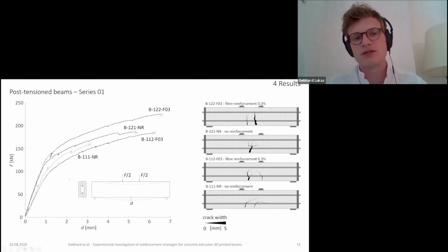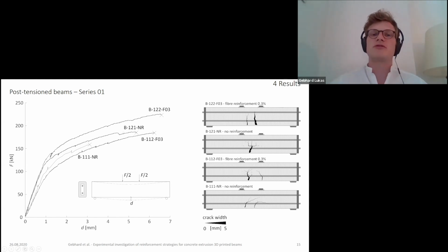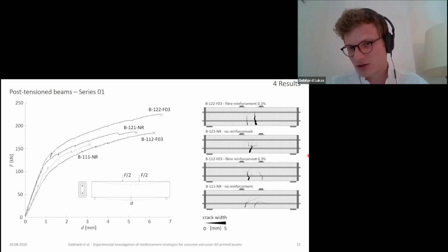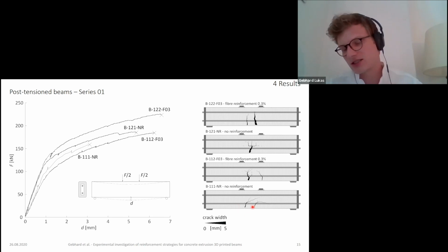So again, only series 1, where you can see the 4 beams. We have the unreinforced one here, the fiber reinforced one, and then the different post-tensioning configurations on top. And what we can see is that they all behave quite similarly. If you look at the crack pattern, we see that we mainly develop bending cracks. For beam 111, you can see that the cracks turn slightly to the right.